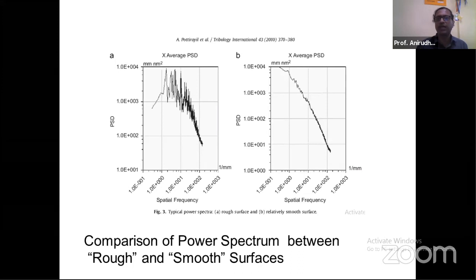But I would like to tell you that the surface which is on the right hand side is more close to being called a fractal, while the other one which is on the left is less likely to be called so. Anyway, that is not our concern. What we did was, we found two parameters belonging to this power spectrum. One is a measure of the area under this curve, which is a measure of the Rq value, the root mean square value. So we use this Rq value of this surface. And then if you see this power spectrum, which is an idea which actually belongs to electrical signal and communication engineering science.